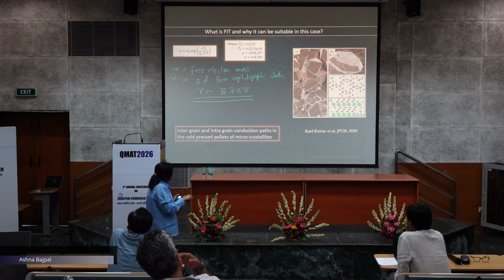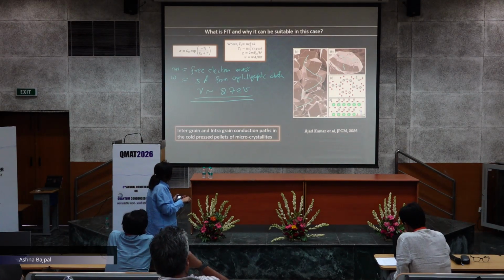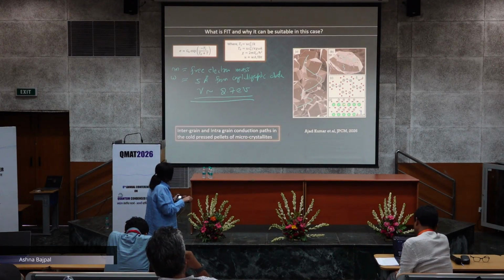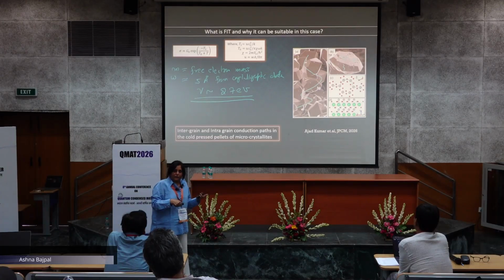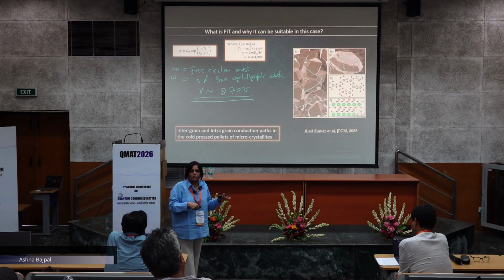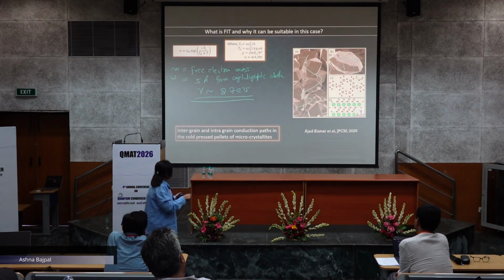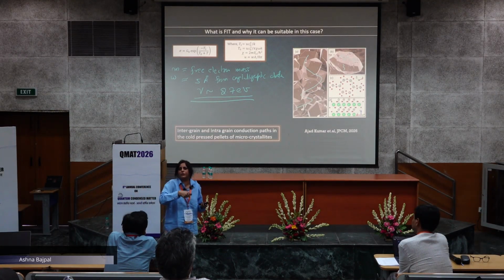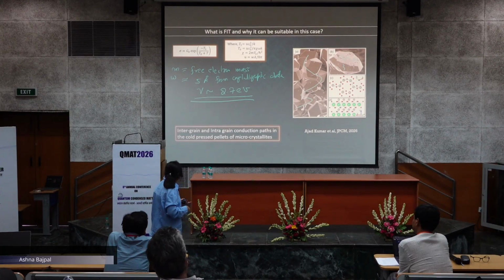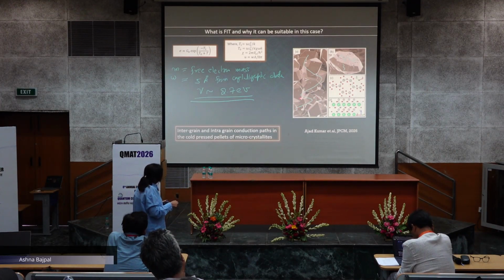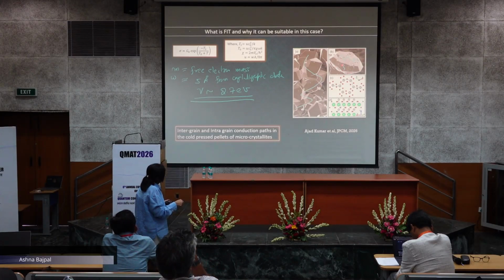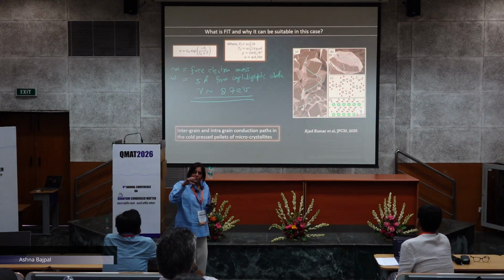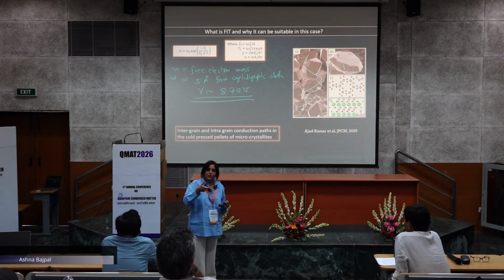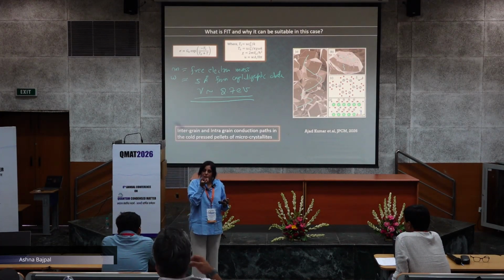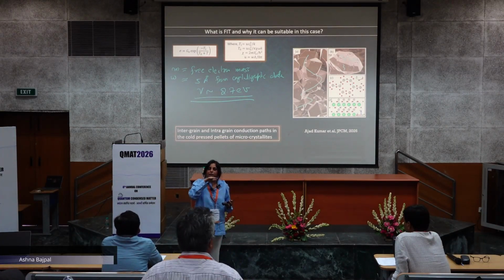In our case, if we consider tunneling from these RuO2 planes through these insulating Sr layers, then we took the crystallographic data. So we took W as 5 angstrom and the free electron mass, and then we got a reasonable potential height V0, and we did it for all the other systems as well. So this told us that we have both possibilities, inter- and intra-grain conduction. But this possibility is an interesting one, because if thermal fluctuation induced tunneling conductance is really valid, then in each single grain you have a conducting layer separated by an insulating layer.